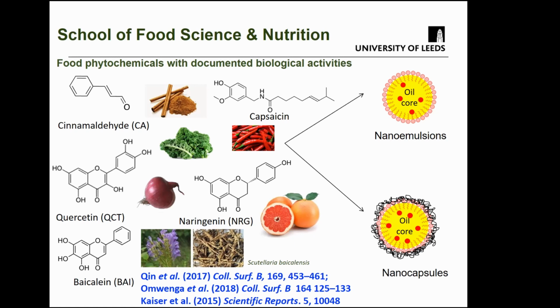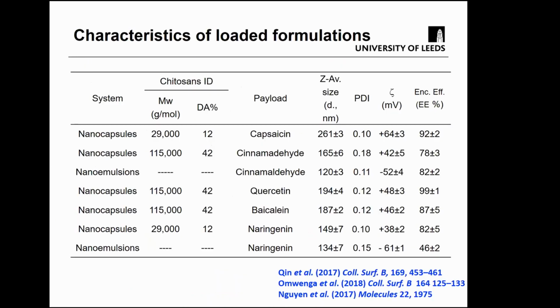emulsions or nanocapsules. So the beauty of this platform is also that it allows us to compare nicely the role of coating with chitosan, because we can just have the bare pristine emulsions without any chitosan surface on them. Okay, then I just show here some of the systems that we've prepared using different chitosans of varying molecular weights or degrees of acetylation.